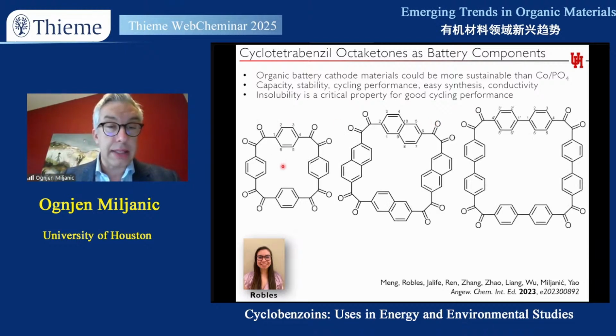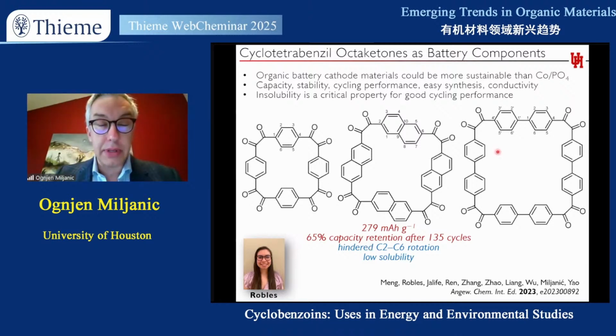And we have tested these three cyclobenzoins, ranging in size, as electrode materials. Why would they be good electrode materials? Well, we thought they could be reduced and produce 8 electrons. So we have tested their capacities, and they're all okay and in line with their molecular weights. But what sharply differed is their capacity retention, meaning the stability of that capacity. And in that respect, the central material was worst, the reason for that being that they were simply too soluble.